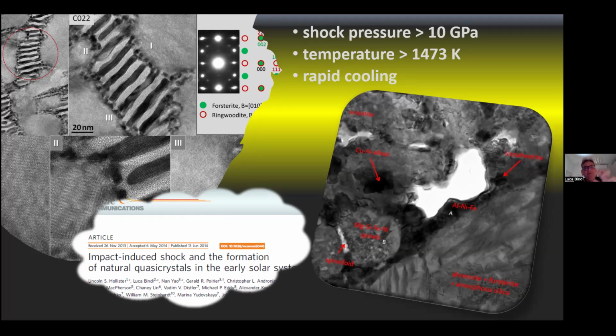Since we have this kind of mineralogical and petrographic features observed in these TEM images, they were symptomatic of very high pressure, very high temperature, and of course, very rapid cooling. All, I would say, corroborating the hypothesis that this kind of material could form in an impact-induced shock occurring in outer space. This was the theory we had in 2013, and we published this hypothesis in Nature Communications. You can see the paper here.